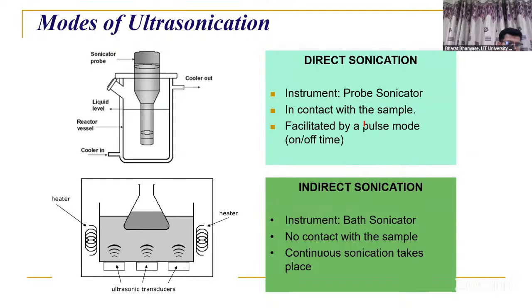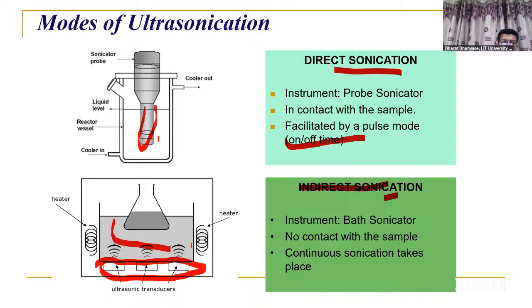So there are two types of ultrasonication. One is direct sonication. That means we are adding the ultrasound probe in the liquid medium, in the reaction medium, and it is operated in pulse mode, on-off type mode. That's why it is direct contact, so your cavitation is generated in the reaction medium. In indirect sonication, we have a transducer here, there is a liquid medium in between, and then the reaction mixture is here. That means your ultrasound probe is not in direct contact with the reaction medium. That's why it is indirect sonication.